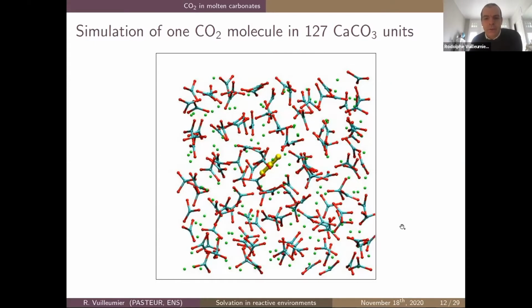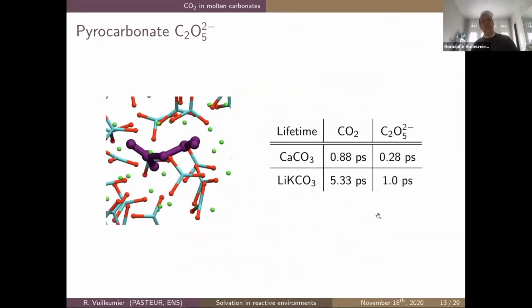So we are in a situation where we have many of these chemical reactions that are quite fast, in a sense, so we can sample them. And what we saw in the meantime is the formation of an intermediate species, pyrocarbonate C2O5 2-, which is reminiscent of H5O2+ that Michele talked about on Monday for the diffusion of protons in water. It has a lifetime of the order of a picosecond, depending on the system we are considering, alkaline earth carbonate or alkali carbonate.